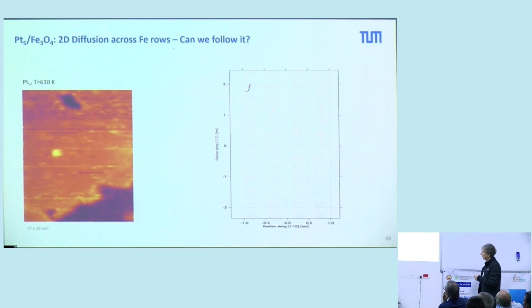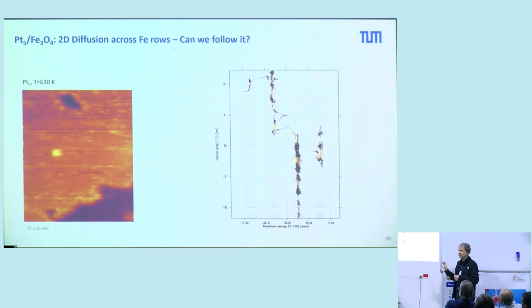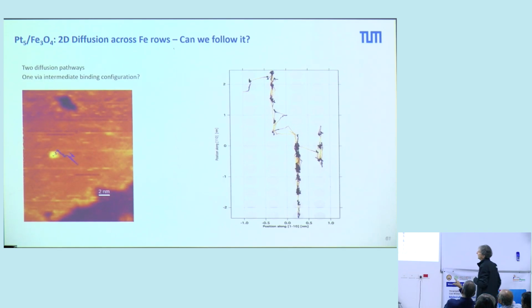If you look a little bit longer, we can also observe that these clusters can migrate over the rows of this iron oxide. And you see here the motion of this platinum 5 on this surface. So they are really dynamic, and this is something you have to consider when doing catalysis. This is real time. That means it has a very dynamic structure, and if you work at high temperature, you have to deal with these kinds of phenomena. There are some preferred sites where you stay for longer. Yes, there is some preference, of course, and then they hop to the other, and they hop to the other. Is it a Lévy flight? No, I don't think so. No. We have other experiments on graphene. There we think that it is connected to this, but here no.